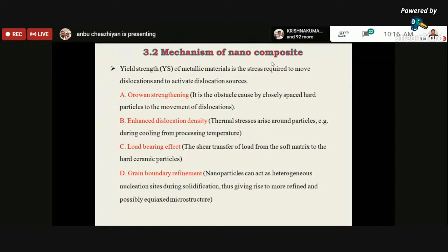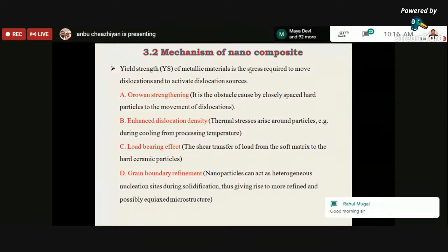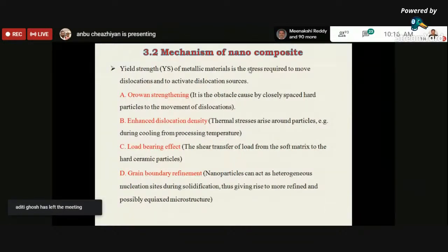In conventional micron-sized particle reinforcement, the reinforcement particles are coarse and the interspacing is large. But in the case of nanoparticles, it is favored with highly dispersed particles. Next we will see enhanced dislocation density. Thermal stresses arise around the particles, since the matrix and reinforcements are generally characterized by different coefficients of thermal expansion. The stress level is often large enough to cause plastic deformation in the matrix-reinforcement interaction region, thus inducing high dislocation density.